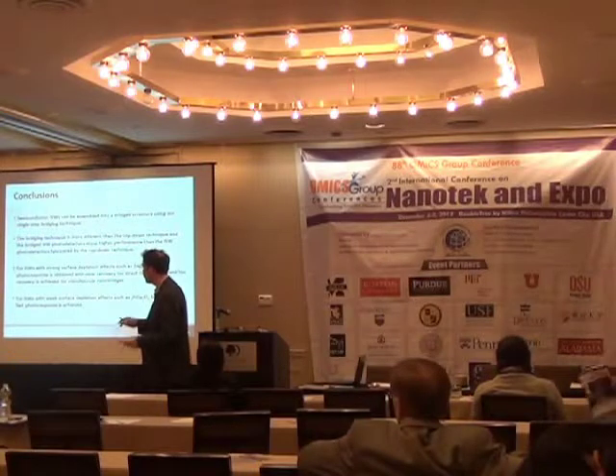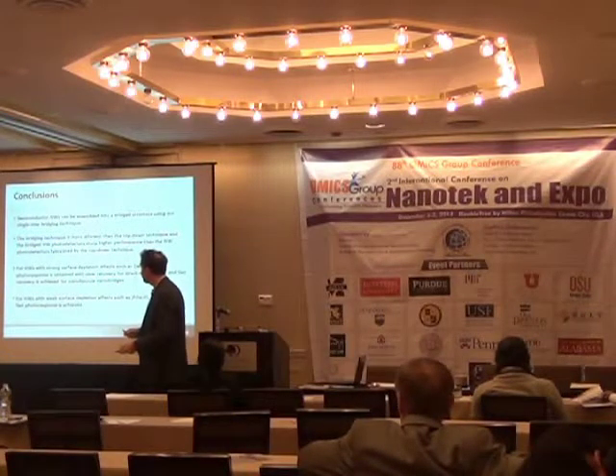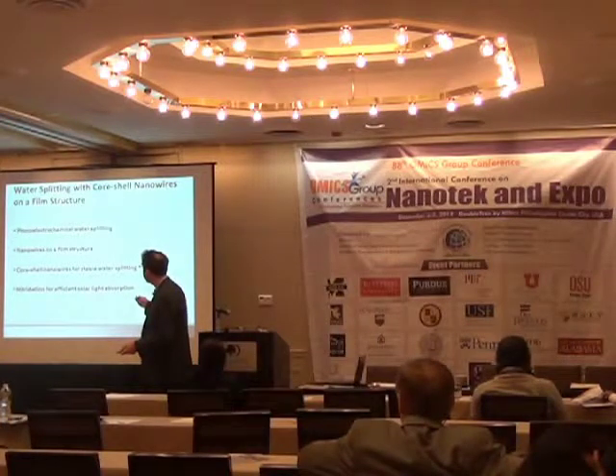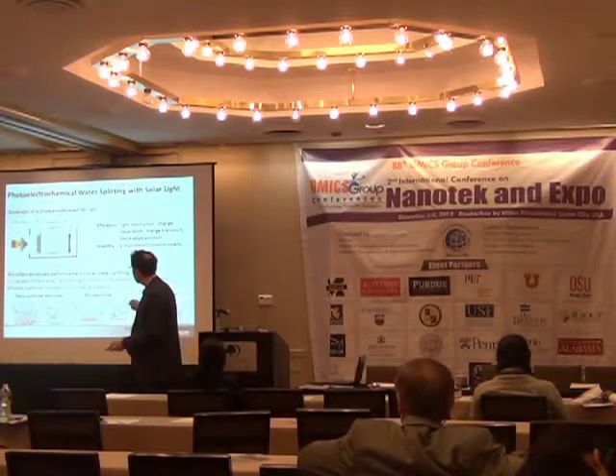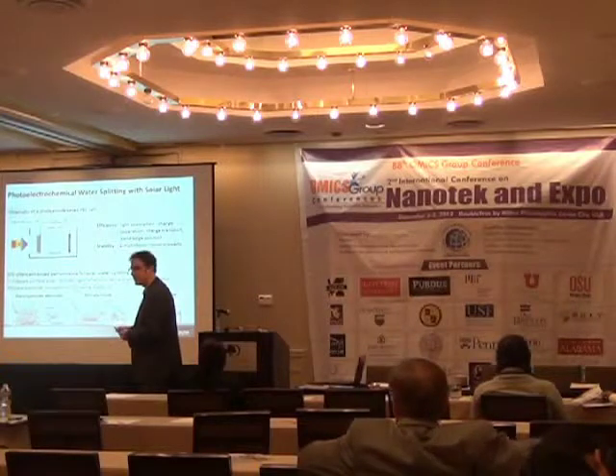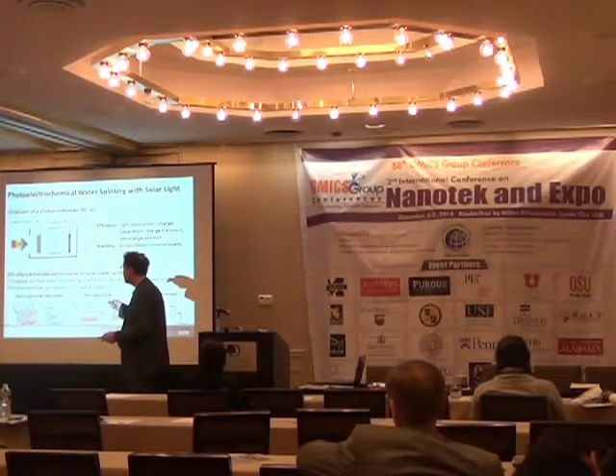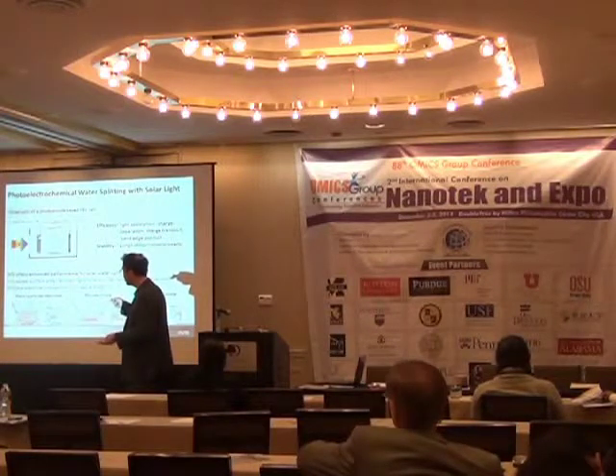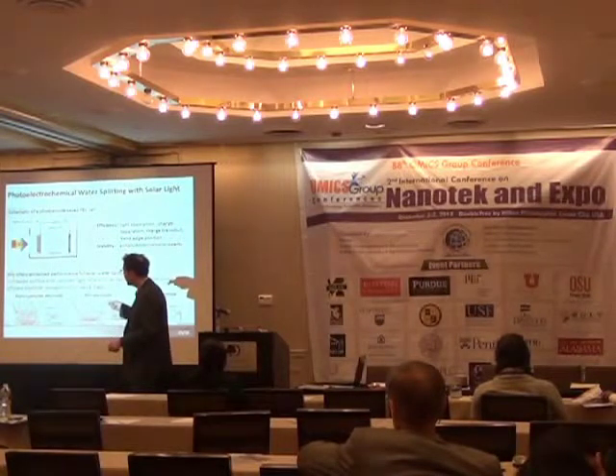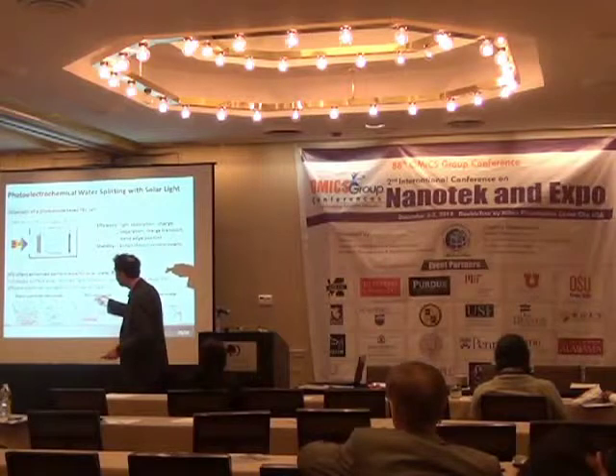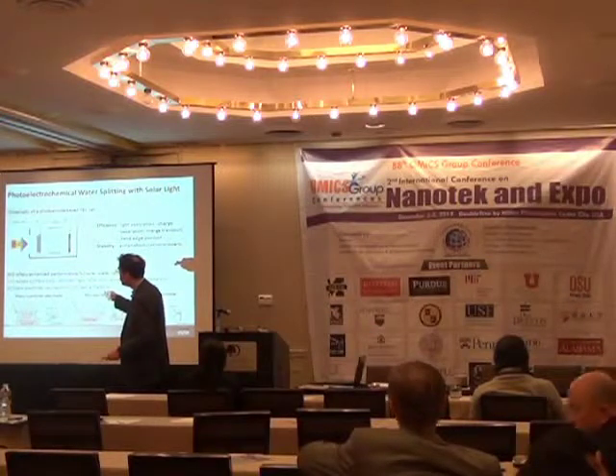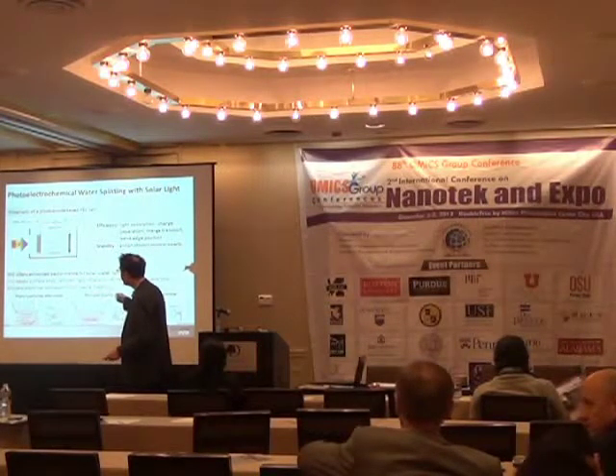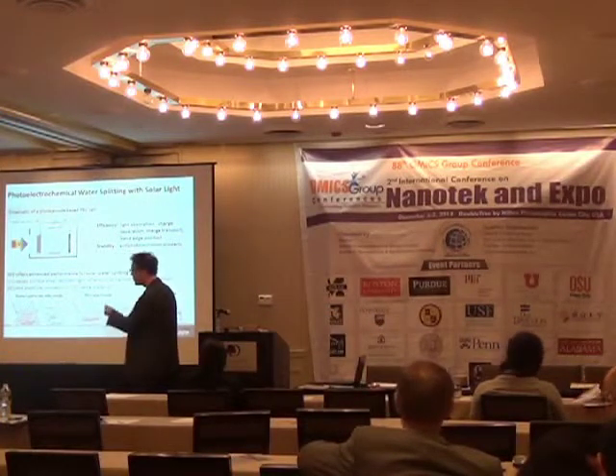So that's the story about the horizontal integration of nanowires. The next point is to use vertical nanowires with a core shell structure that I will explain right now. So we do water splitting with these vertically aligned nanowires. For water splitting, what we have is a photoanode and a photocathode. But what I show in this presentation is a photoanode story. Okay? So the light is coming from the left side here, you make the photoanode, and you oxidize water and form oxygen. Here on this side, on the cathode, you will form hydrogen. You can do the reverse as well.